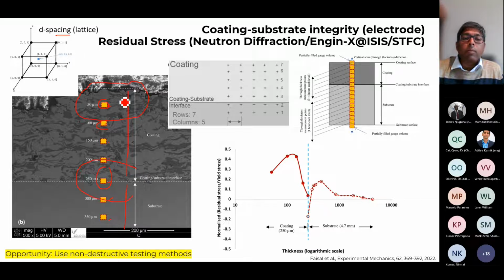So you would not want to have a huge gradient through thickness and a huge gradient at the interface. So these will not be good enough if you're applying any external load. So it will fall, it will delaminate, or all sorts of degradation will happen. So you can use this method to find out how even you can put this coating at high temperature and do the testing non-destructively.